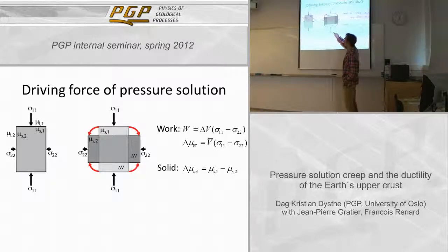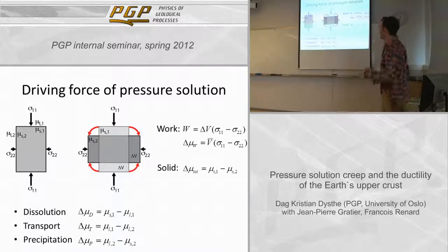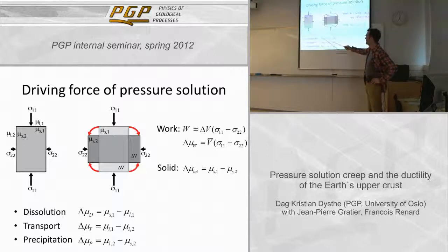Now, we'll see that if we go into more detail, there is a solid chemical potential and a liquid chemical potential, and the difference drives the dissolution. The difference between the chemical potential in the liquid here and liquid there drives the transport, and the difference between the chemical potential in the liquid and the solid drives the precipitation. But in total, all you have to know about is the difference in chemical potential of the solid on this face and this face. These are just intermediates. So this is just what I said. These are the driving forces for the three different steps of the process.